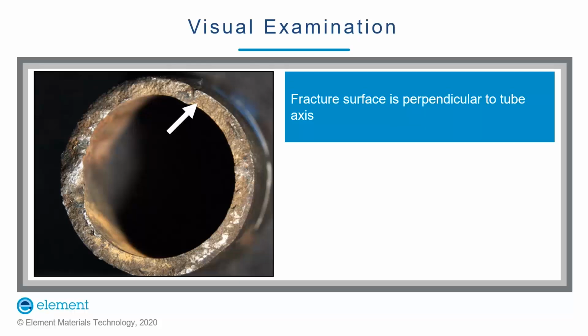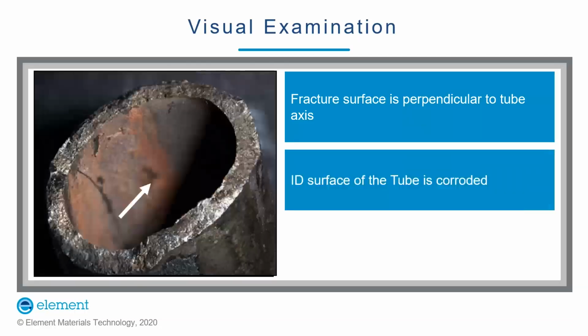Fracture surface appeared to be brittle. Additionally, corrosion was observed on the fracture surface, shown by the white arrow. Corrosion was also observed at the ID surface, shown by the white arrow.